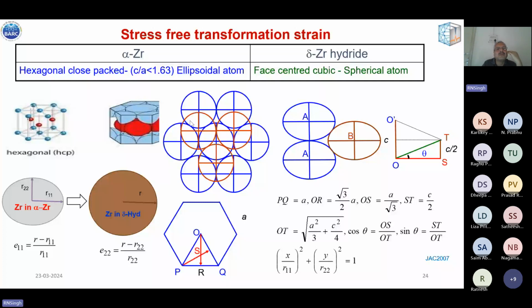If you see the zirconium crystal structure, it has a c/a ratio less than ideal. As a result, he assumed an ellipsoidal shape of the zirconium atom. In the case of hydride, since it has a face-centered cubic structure, we can assume a spherical shape of the atom. Then based on the semi-major and semi-minor axes of the zirconium atom, one can calculate the transformation strain. The transformation strain E11 is the one along the hydride platelet, and E22 is along the normal to the hydride precipitate. Whatever stress-free transformation strain is determined using atomic dimensions is valid for the hydride precipitate.